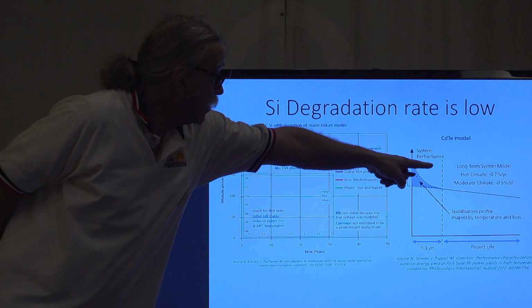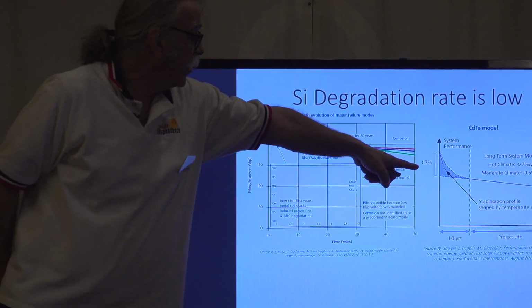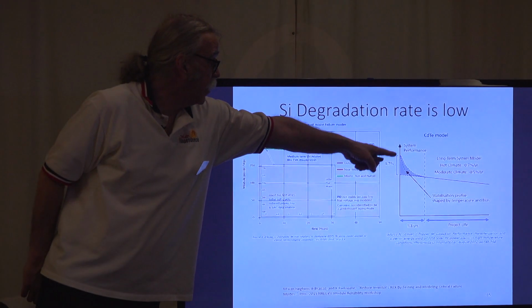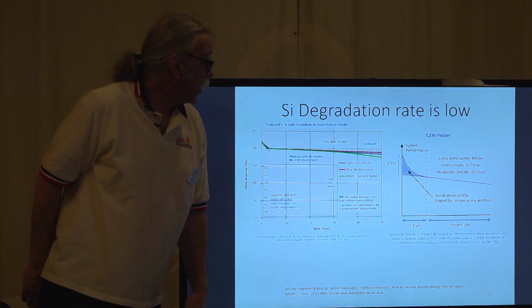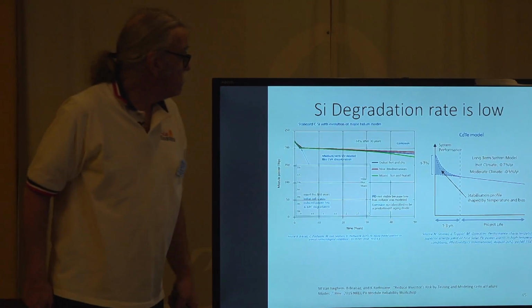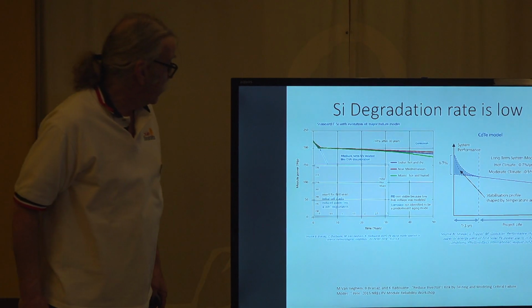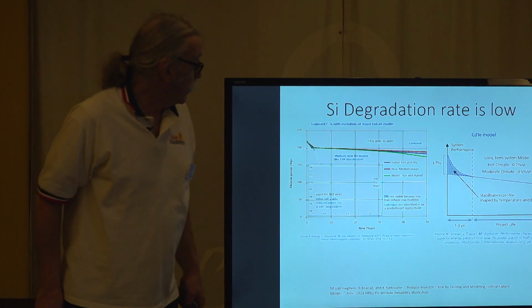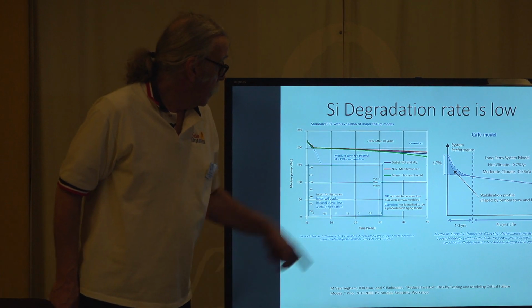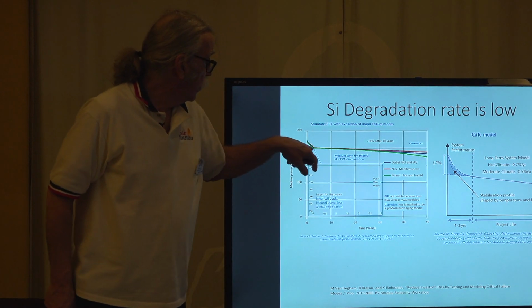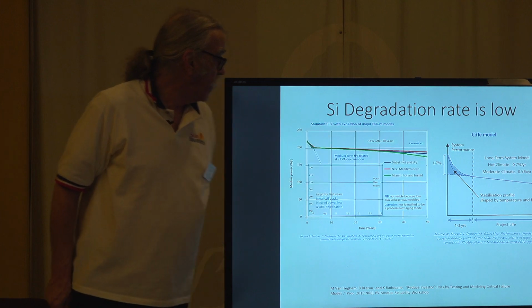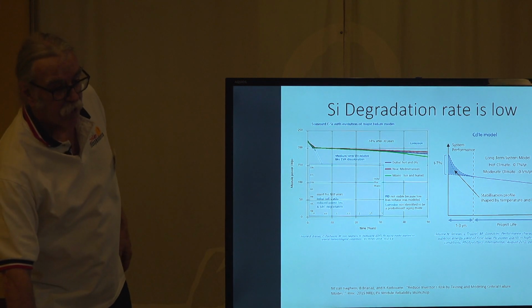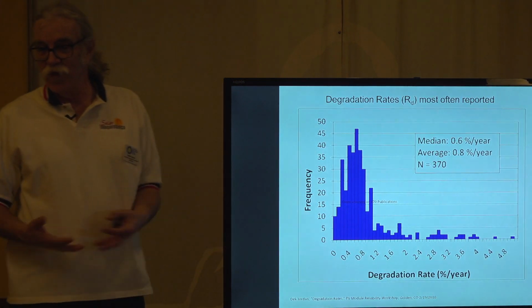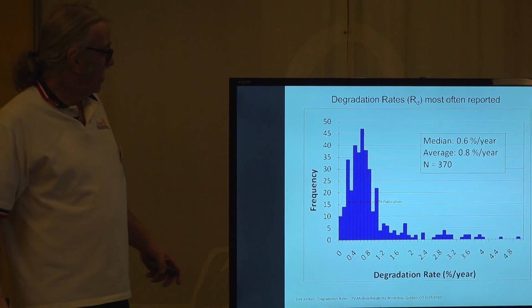I showed this already, but the degradation rates, again, a hot climate is 0.7% per year, that would be like Phoenix. Hot, humid, it might be even a little bit higher. Moderate climate, that'd be like here. It's a lower degradation rate. They have different degradation rates for different climate zones. Miami, that's the green curve here. And notice it degrades more. And that's silicon. Why? Because it's hot and humid, it just drives moisture in, it just corrodes stuff.